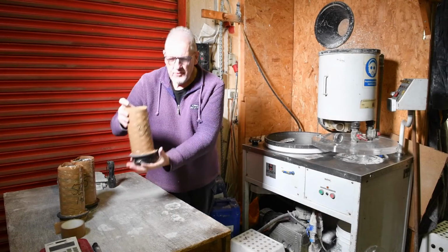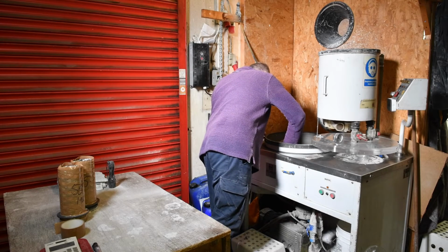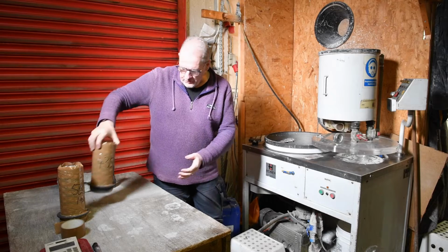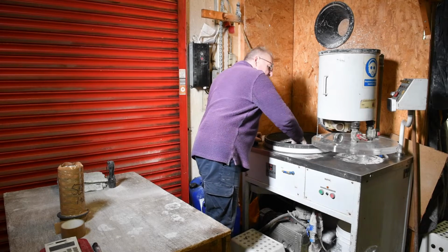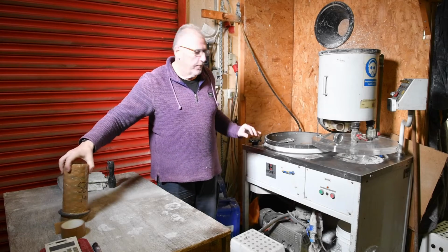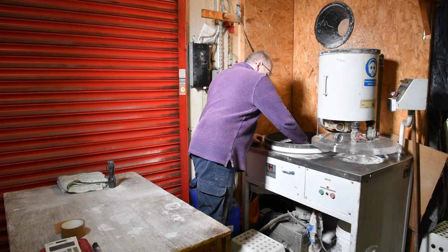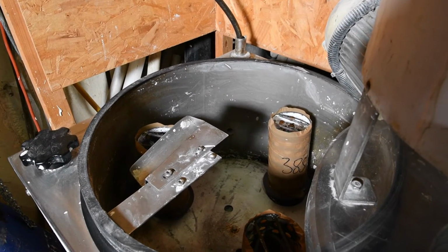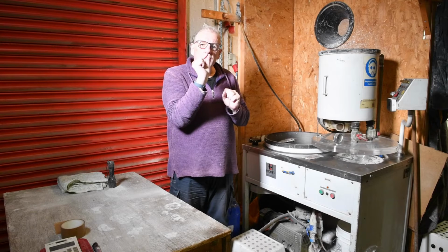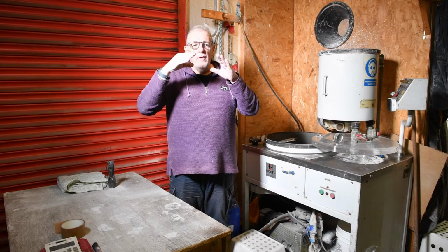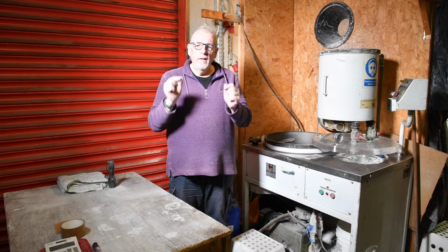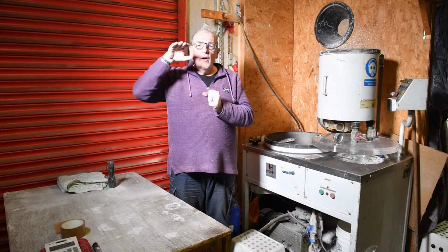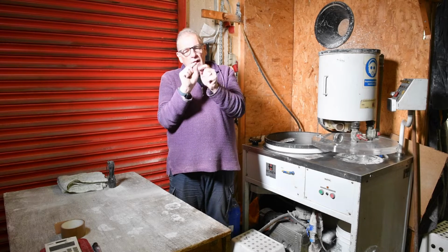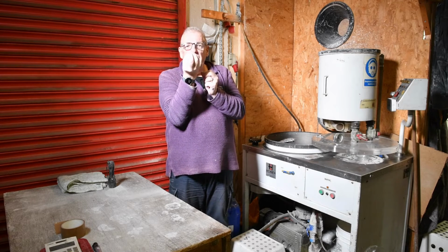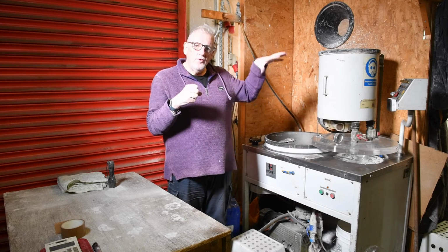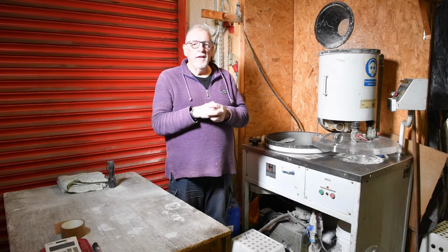Right, so the flasks then are taken and put into this machine, and this machine mixes the investment, which is essentially plaster, under vacuum. The reason that it mixes it under vacuum is so that when it fills the flasks, we don't get any trapped air nodules in there, because when the wax is melted out, the metal will fill where that air pocket was. So sometimes you'll see castings with a tiny little nodule on there. That's because all of the air hasn't been sucked out during the mixing of the investment at this stage.